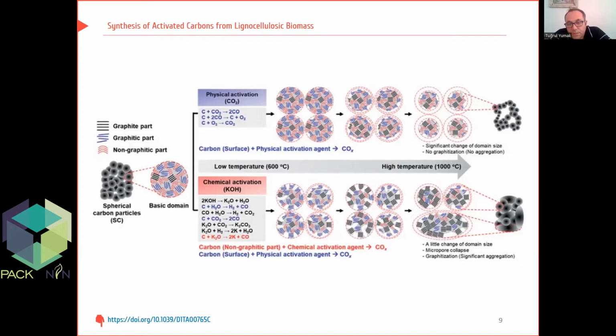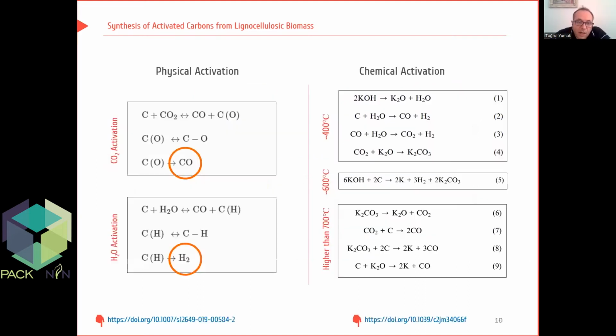Furthermore, since the chemical activation reduces the amount of non-graphitic parts, chemically activating a carbon material at a relatively high temperature can enhance its crystal structure. In other words, chemically activated carbon materials contain relatively low proportions of non-graphitic parts.